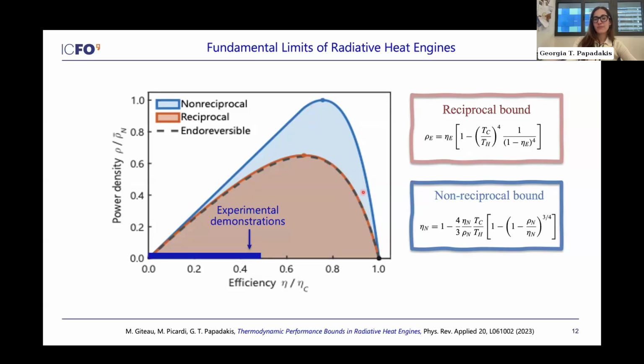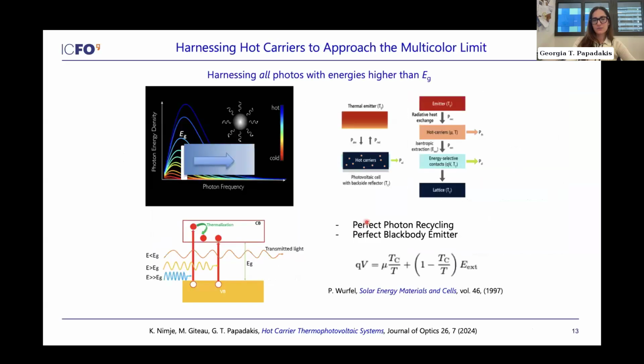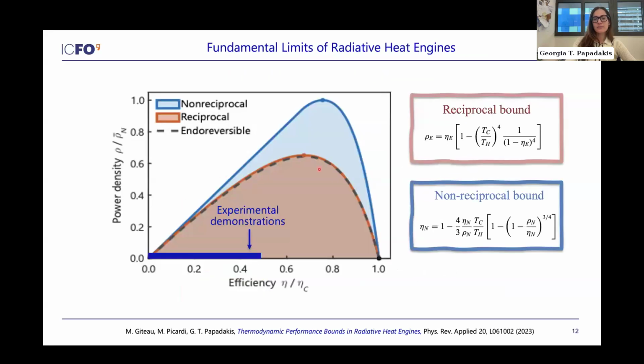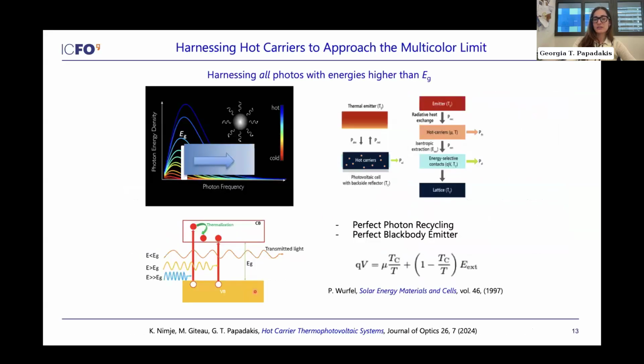So this orange curve basically demonstrates the multicolor limit. If I take infinite PVs and put them one next to the other, and I separate the spectrum into infinitesimal spectral ranges and each cell converts a little bit of the spectrum, I get this trade-off between power density and efficiency. And as I said, this is just to show that there's really infinite room for improvement in TPV research. One way to actually reach the reciprocal limit, the multicolor limit, is what we discussed in this paper here.